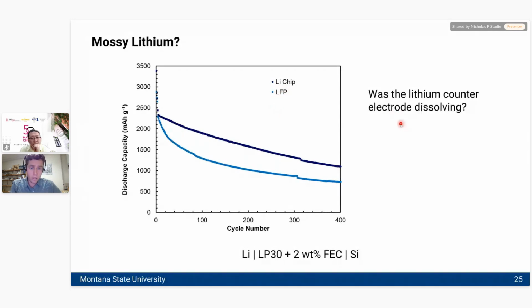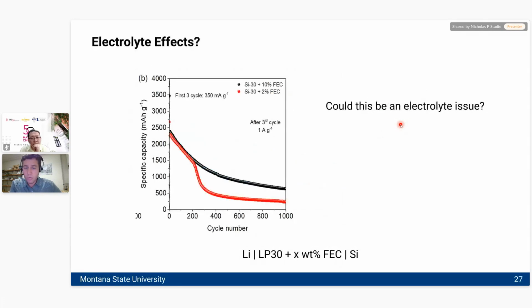And so we started investigating LFP, lithium iron phosphate, as a potential counter electrode to try to solve this problem, but it did not solve the problem. We still had lots of capacity fade, and things were even worse basically for LFP than they were for the chip. So we went back and had to look into the electrolyte chemistry.